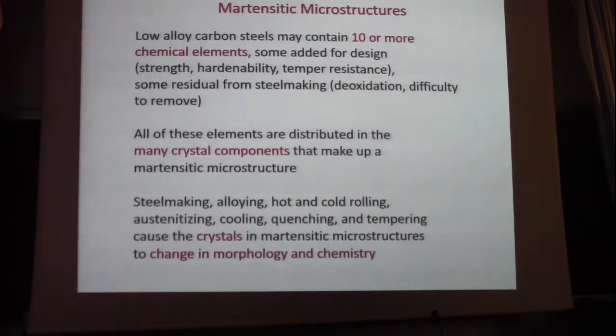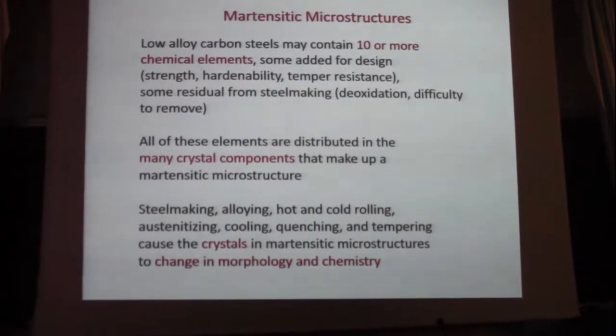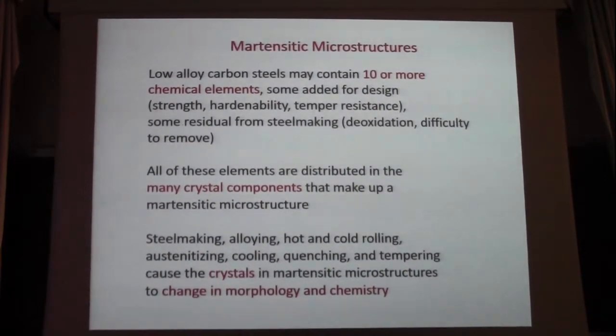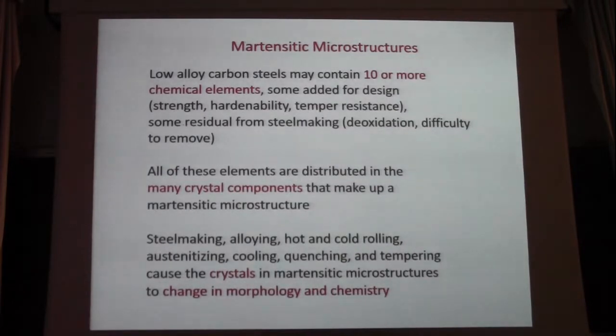Now, what the quench and tempering does is produce martensitic microstructures. And what we've been learning is that steels, certainly mostly iron, carbon, but there may be 10 or more other chemical elements within the microstructure of steel. And some are introduced by design to make the steel hardenable, to increase strength, to increase toughness and fracture resistance. But some of these elements that are present in steel are difficult to remove from steel making, and they can create problems. In particular, phosphorus is an element that one has to be very careful of controlling.